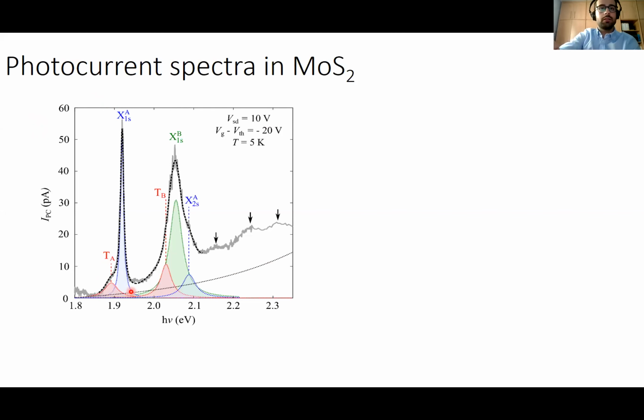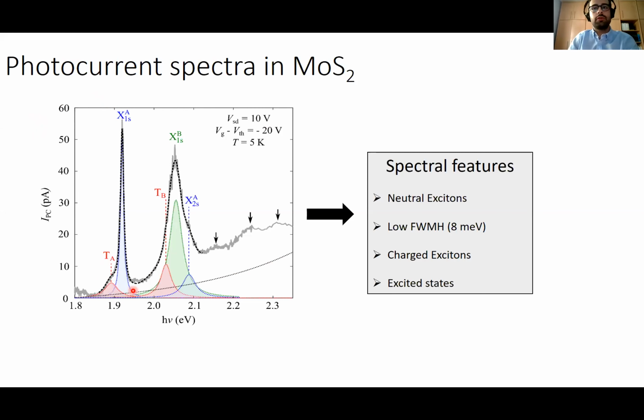And these spectral features we associate to neutral excitons, that are here A and B. Also, the charged excitons or trions that are plotted in red. And we observe also some excited states of the excitons. And we are able to resolve all these peaks because we have very narrow peaks, on the order of 8 milli-electron volts, that allow us to see a lot of spectral features.